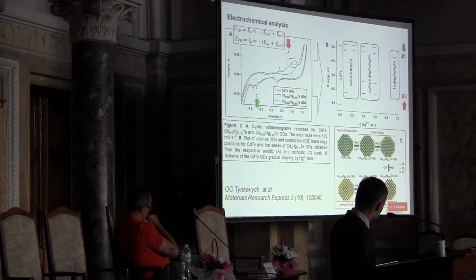Then in between there is something like a transition, and still you have a core, which is still cadmium telluride. And because the particles are quite small, you can still see most of them in the spectra as well, and you can probe it a little bit electrochemically. And if you increase the concentration, you actually end up with something like this.